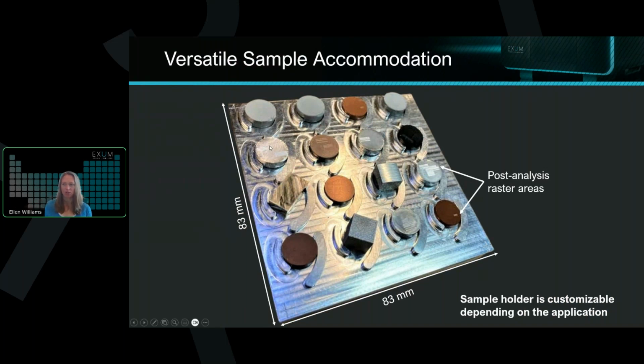For powders, you can see we have some examples here where we're pressing them into a pelletized puck and just applying a little bit of hydraulic pressure. If you want a really quick analysis and don't even want to spend the few minutes putting it into a hydraulic press, you can just use a vacuum compatible carbon tab and just dip it into the powder of interest. You also may need to do that if you only have a very limited amount of powder. So that's potentially similar to a SEM-EDS type sample prep that some people may be familiar with.